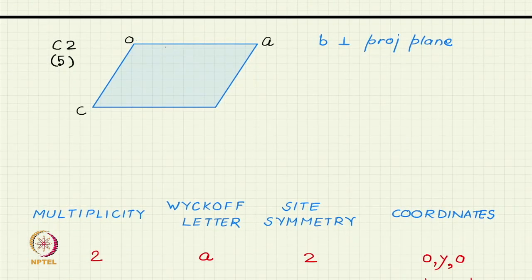Now, C 2 is another interesting example, but by the letter C we mean C centering. C centering means the AB face. So, I have lattice points at the corners, but I have an additional lattice point on the AB face, which in the projection is there and it is on the center of the AB face. So, it will come there, but these will have a height half in the y direction.